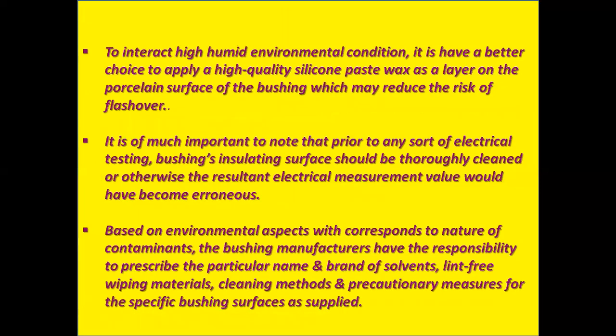To interact with high humid environmental conditions, it is a better choice to apply a high quality silicone paste wax as a layer on the porcelain surface of the bushing, which may reduce the risk of flashover. It is of much importance to note that prior to any sort of electrical testing, the bushing's insulating surface should be thoroughly cleaned, or otherwise the resultant electrical measurement value would become erroneous.